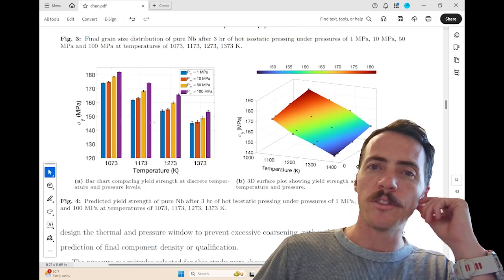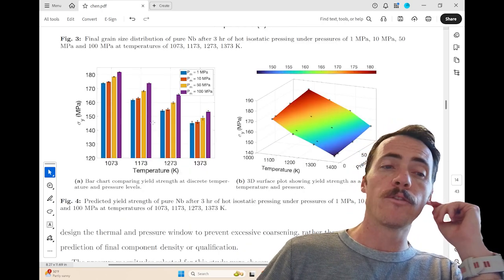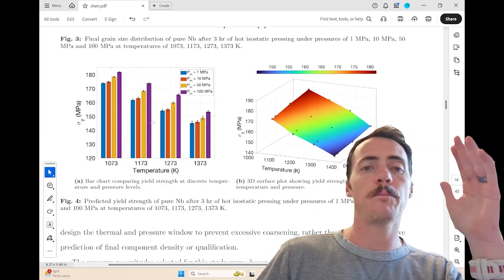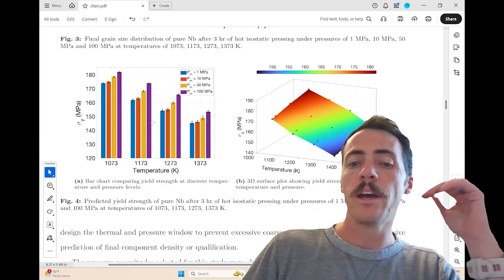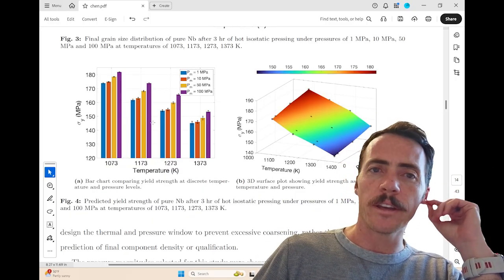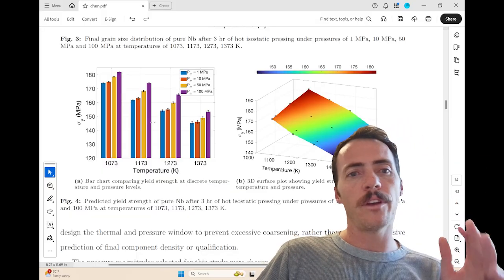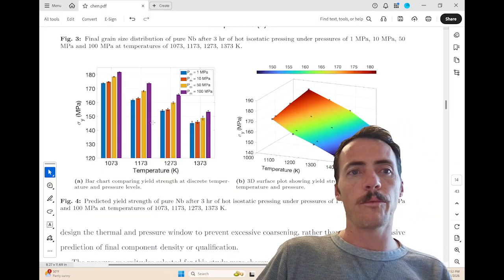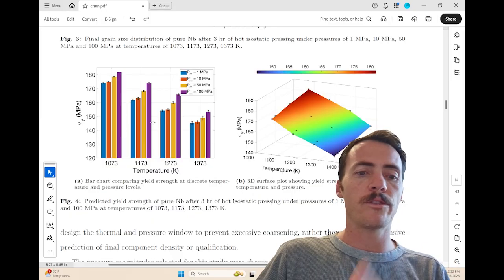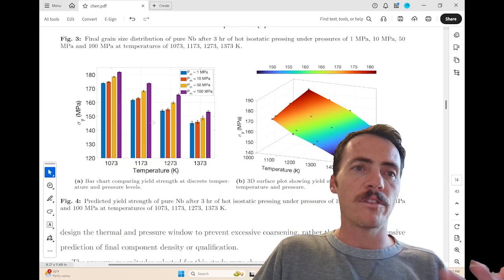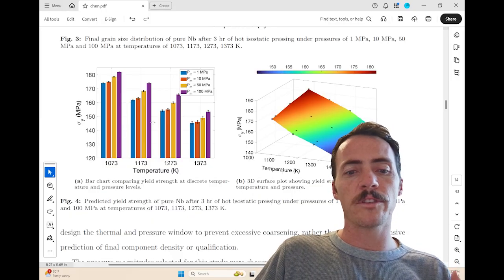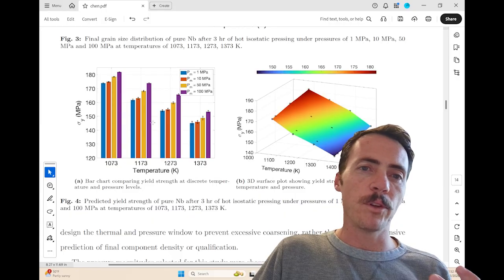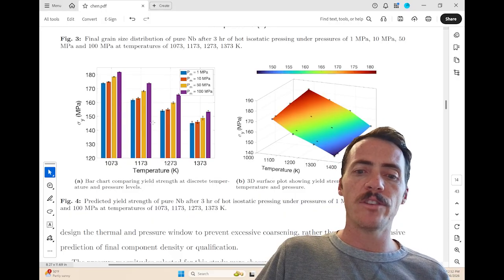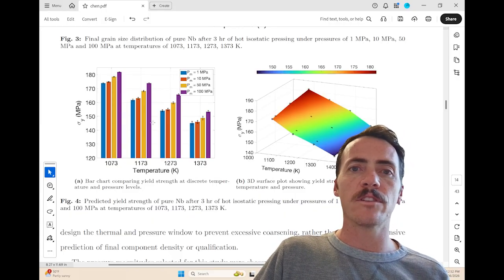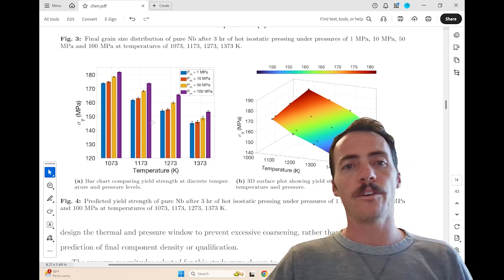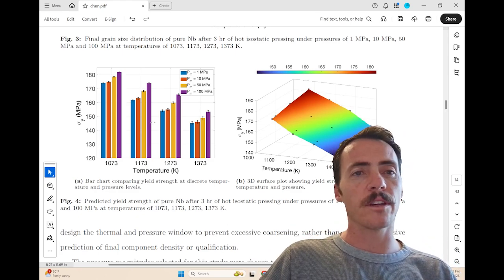A nice way to summarize these results is shown here in figure 4. In figure 4, you see the yield strength as a function of hipping temperature and pressures. And there's some subtleties, right? If you take 1073 Kelvin, the benefit that we saw before is actually reduced. As you go from 50 MPa to 100 MPa, that benefit in terms of the strengthening shrinks to less than 2%. So it's nice that they've built a tool here that's going to allow engineers to make relevant decisions about the cost benefit of different pressure or temperatures of the hipping process.